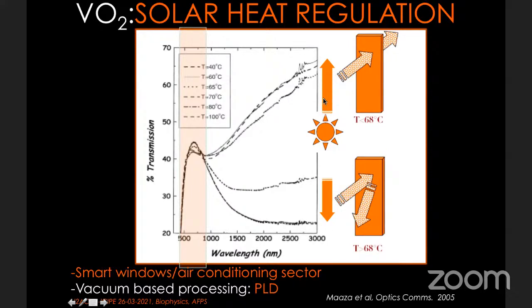What does it mean? That means a glass coated with this VO2, at low temperature, allows the solar heat from the sun to be transmitted. When it's hot, when the atmosphere is hot, this coated glass will reflect the infrared. And therefore, it stops the heat when it's hot outside, and it allows heat to come in from the sun when it's cold in the winter.